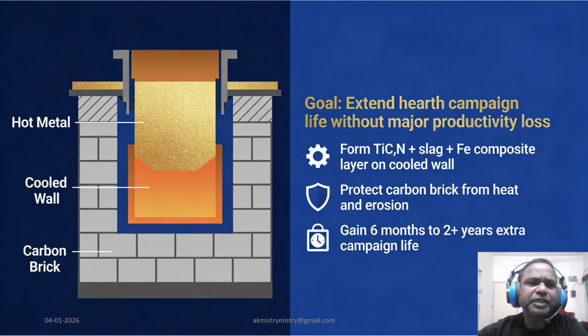Our primary objective is to extend the hearth campaign life by anywhere from 6 months to over 2 years without causing significant productivity losses. We achieve this by forming a composite layer consisting of TiCN, slag and iron on the cool wall. This layer acts as a shield and protects the underlying carbon brick from intense heat and chemical erosion.